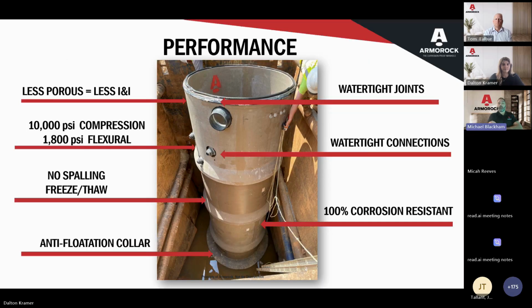So let's talk a little bit about some of the good performance aspects of polymer concrete. Because polymer concrete does not use that water and cement paste, it's far less porous than conventional concrete. This can also help reduce porosity and absorption, which can also minimize inflow and infiltration, which some people would refer to as I&I. That lower absorption rate also can improve the freeze-thaw durability by preventing water from entering the material and expanding during those freeze-thaw temperature cycles.